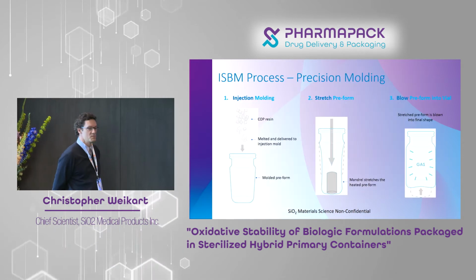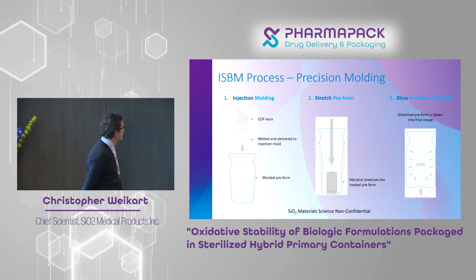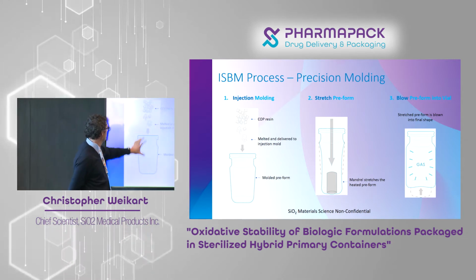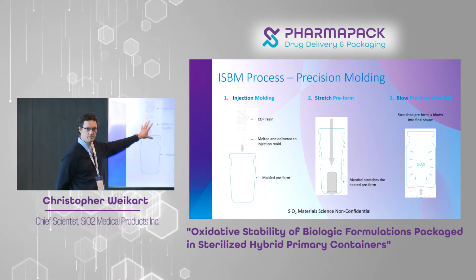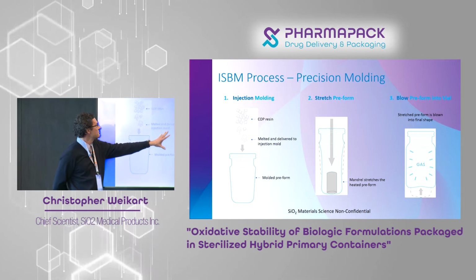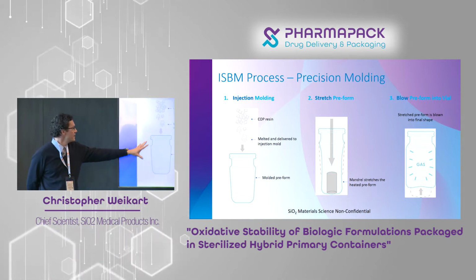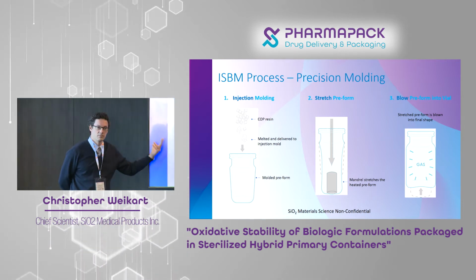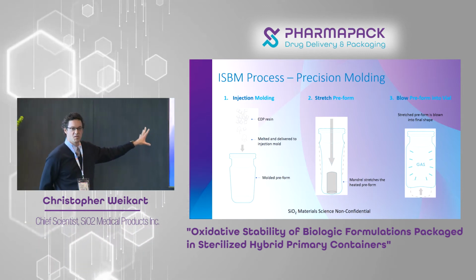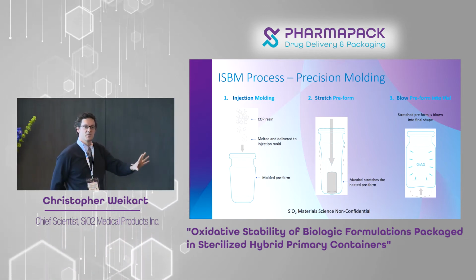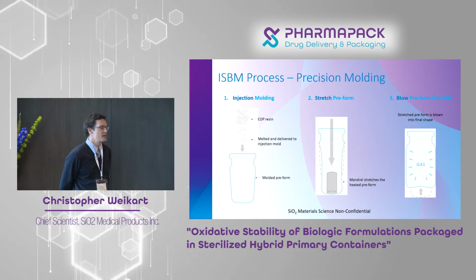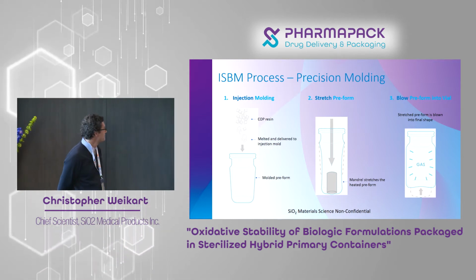So it starts with molding. Basically, we injection mold a preform out of this COP resin. We stretch and blow it into a final mold, and you get either a vial or, in this case, it's injection stretch blow molding, so this is specifically for vials. In the case of syringes and cartridges, you'd be injection molding it.